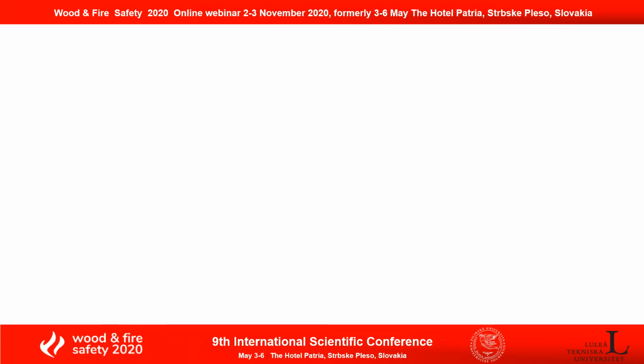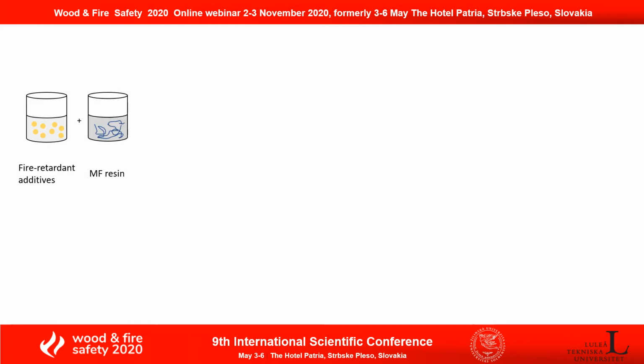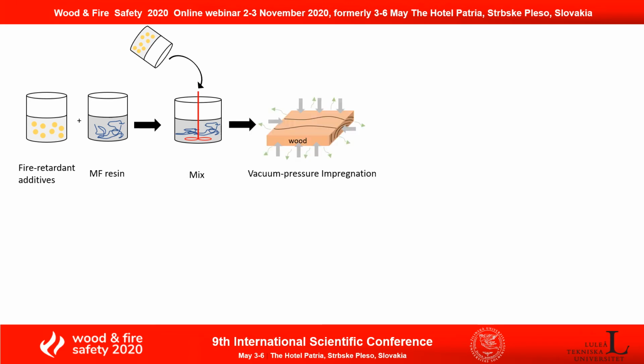And here shows how I performed an experiment. First of all, I took these fire retardant additives, urea phosphate and boric acid, and dissolved them in water. Another batch is MF resin prepolymer, and I simply mixed them and then did vacuum pressure impregnation. And after that, I applied some heat to let these polymers polymerize within the wood structure.